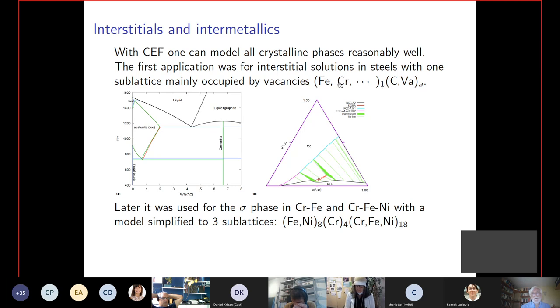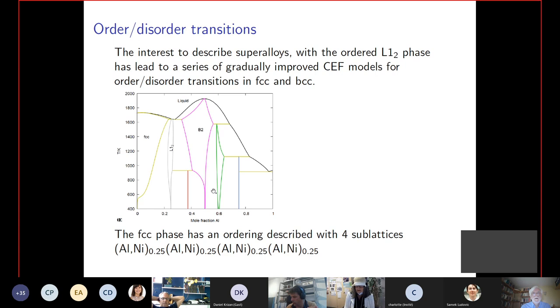And then you can go on to do other systems. You have interstitials, like when you have carbon in steels, you can get phase diagrams for the iron carbon system, a stable and metastable one. You can add chromium and calculate the iron chromium nickel system, where you have intermetallic phases like a sigma phase, which you also describe with the different types of ordering. Here you don't have any disordered state. Sigma is never completely disordered, but it has always some substructures. And then one can go on to describe superalloys like aluminium nickel, and you have an L12 phase, which is the important one when you want to have phases which are stable at high temperature and strong. The B2 structure is even more stable, but it has less good mechanical properties.